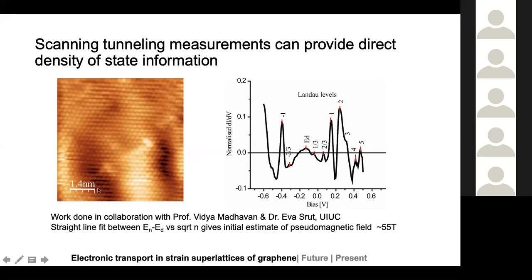and that looks really cool. So by looking at the Landau levels and the energy where they occur, you can calculate the pseudomagnetic field which is generated in the system. The preliminary measurements which we have done show that a pseudomagnetic field as high as 55 Tesla can be generated, which is significant because in the lab, we can generate a maximum of 7 or 8 Tesla magnetic fields. It's really impossible to go beyond that. So to be able to have such a high pseudomagnetic field in the system opens up the opportunity for seeing a lot more quantum phenomena.